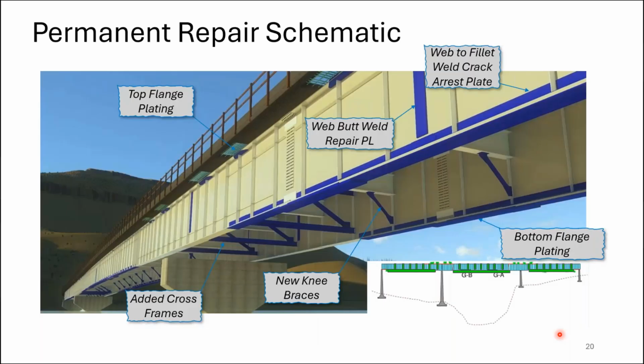So we had top flange plating because we did not want to open up the entire top flange section and have a large portion of open deck during the permanent construction that would have to close the bridge. We actually went with local repairs in the top flange sections and tested the fillet weld for the entire length in order to make sure that we didn't have any of those flange to fillet or the fillet weld cracking. These were 50 KSI so that they could start working on them immediately, and then required a small deck removal in order to get those bolts in.